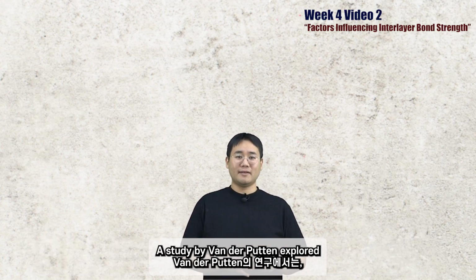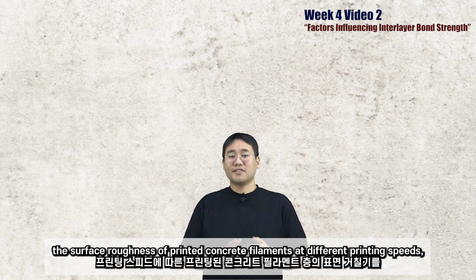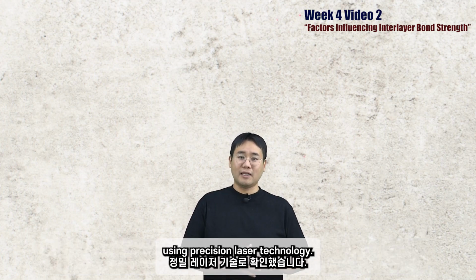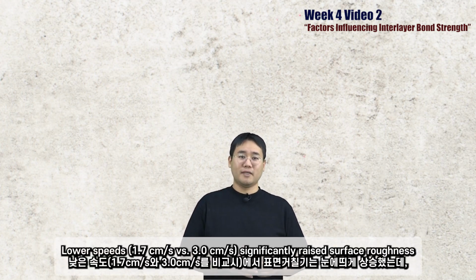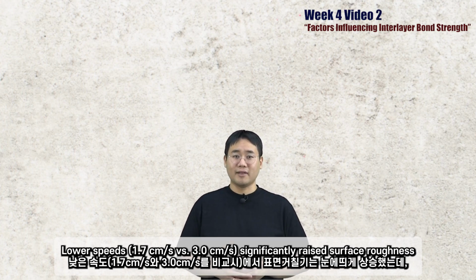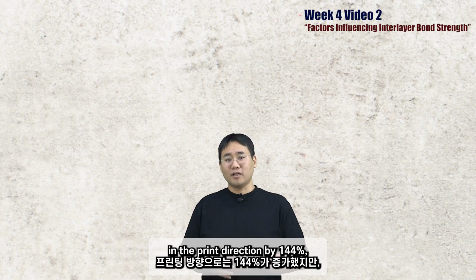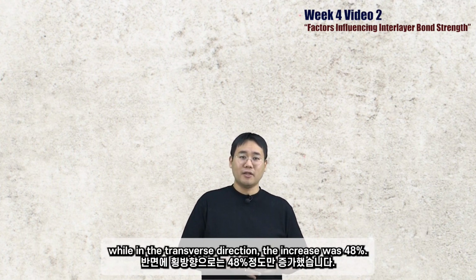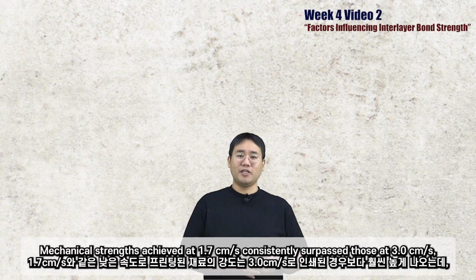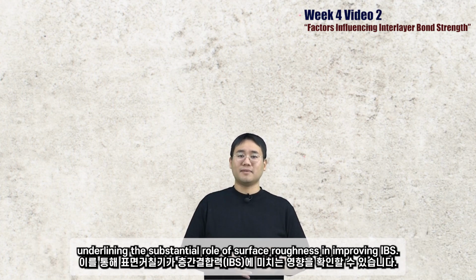A study by van der Putten explored the surface roughness of printed concrete filaments at different printing speeds using precision laser technology. Lower speed, like 1.7 centimeter per second versus 3.0 centimeter per second, significantly raised surface roughness in the print direction by 144%, while in the transverse direction, the increase was 48%. Mechanical strength achieved at 1.7 centimeter per second consistently surpassed that at 3.0 centimeter per second speed, underlining the substantial role of surface roughness in improving interlayer bond strength.